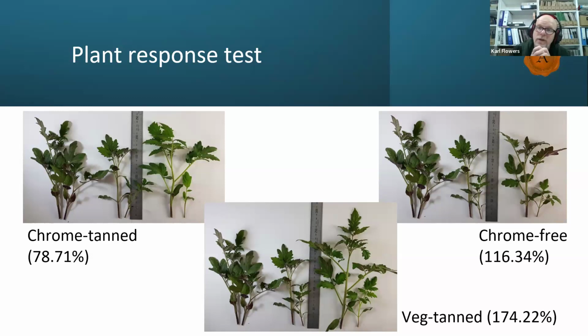On the right-hand side, the chromium-free leathers did grow more than the blanks, and that would be a very good result in terms of the ecotoxicity if somebody was screening plants grown in a chromium-free compost. So absolutely no problems with the plants, no deformations, good plant growth, higher than what we would expect, and of course, a very favorable material that could be placed onto an agricultural land.